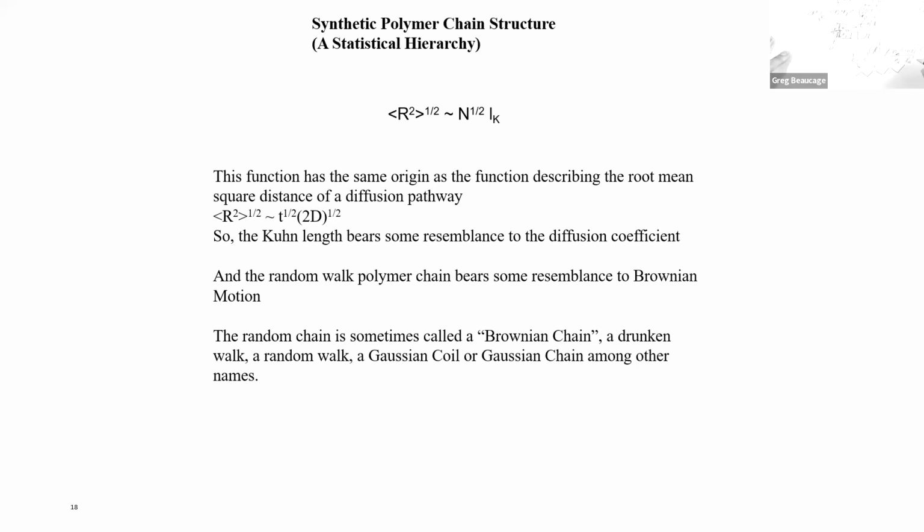And then the number of Kuhn lengths gives R squared. And that would be the step model. It's going to take a step. So it turns out 7.6 is how many ethylene units are in an actual step, due to this rotational conformational issue and whatever else happens locally.